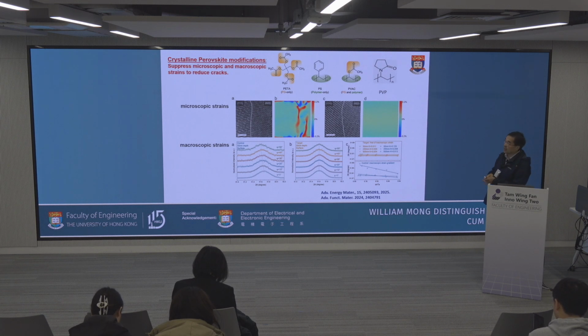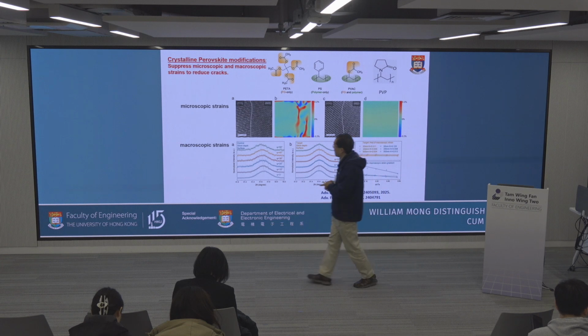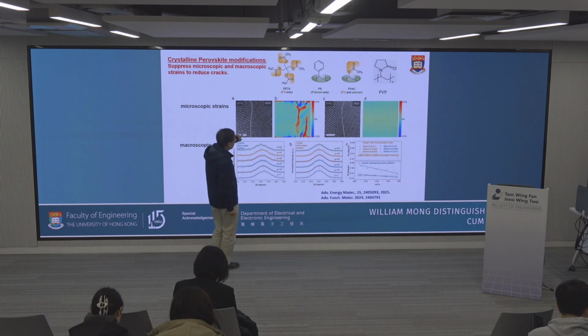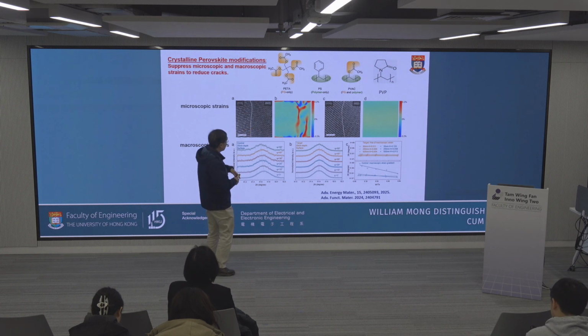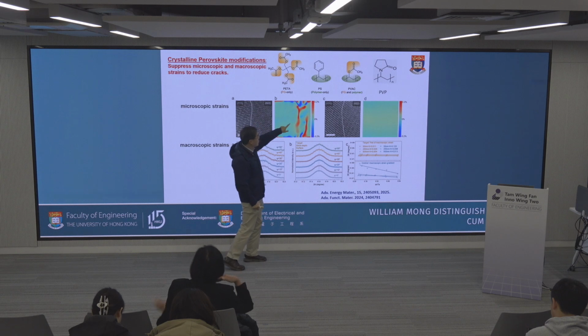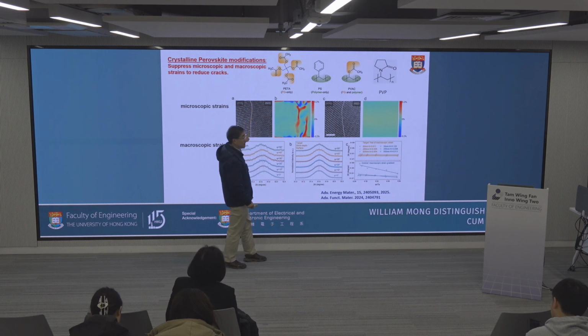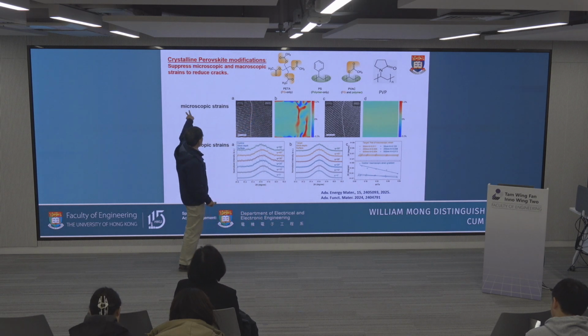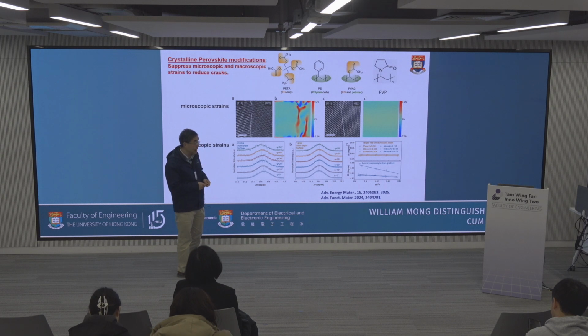Nevertheless, go back to the perovskite itself. In the perovskite itself, you have a crack. So what we do is we try to solve the problem of typical perovskite. We can see that typically, when we form a perovskite film, this is a boundary between two grains of the perovskite. This is STM. From the STM, you can extract the stress of the perovskite. We can find that from the top view, stress is created in these regions, okay? This is what I just name a microscopic stress.